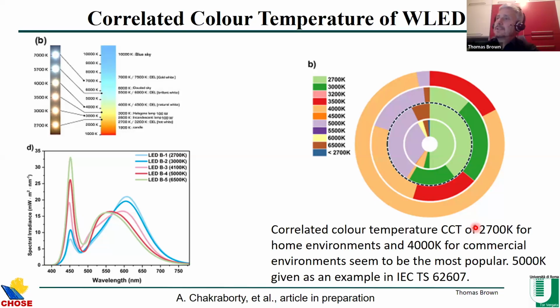So we conducted a study where we see that in residential areas, most of the correlated color temperatures sold by online vendors like Amazon is around 2,700 Kelvin, whereas for office and commercial spaces, it's more around 4,000 Kelvin. Now, the IEC came out last year, on the 27th of July 2023, with a technical specification which gives some recommendations on how to measure photovoltaic devices indoors. Their examples are white LEDs or compact fluorescent lamps at 5,000 CCT.